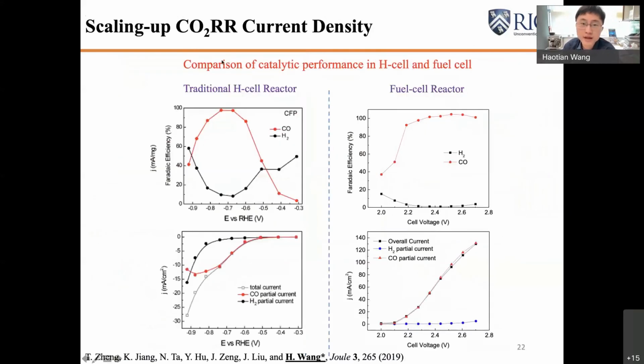And as a result, as you can see, if we are using the exact same type of catalyst but a different type of reactor, we can see the current density can be improved by one order of magnitude. But our selectivity for CO can be maintained at more than 98%. This is a much improved scenario compared to the traditional H cell reactor.